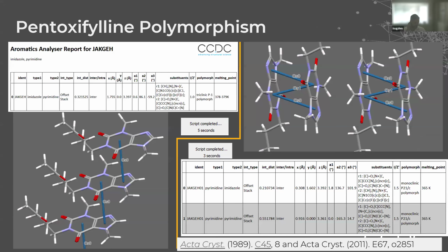When we run the aromatics analyzer on these two polymorphs, what we can see is, if you look on the far left, the melting point is 378 to 379 K. Compare that to the image on the right, which has a melting point of 365 K. So a higher melting point suggests more stability.